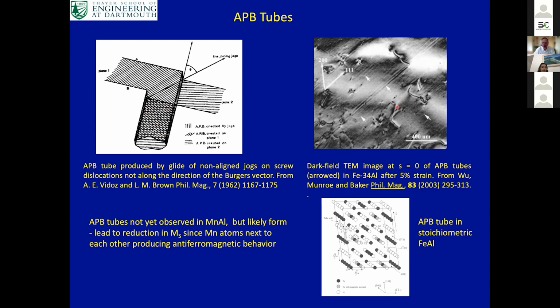And you can see an example from some work of our own for APB tubes in iron aluminum here, and there's a little model of what it looks like here. So these haven't been observed in manganese aluminum, but since the dislocations in manganese aluminum are undoubtedly coupled by an antiphase boundary, it's very likely that they occur.